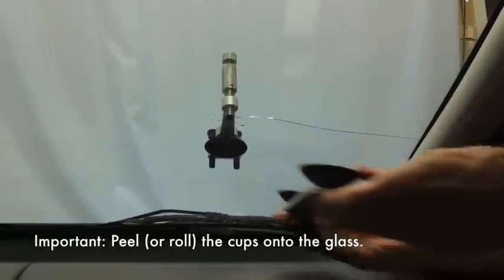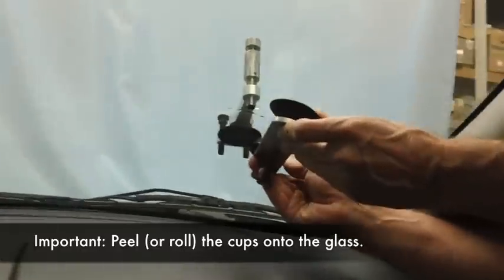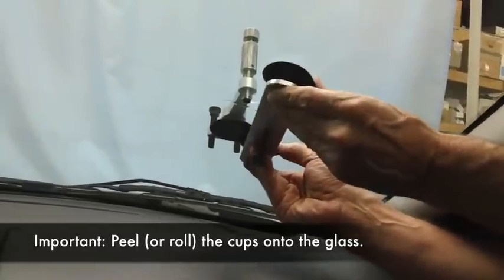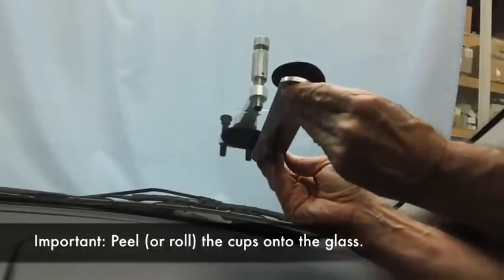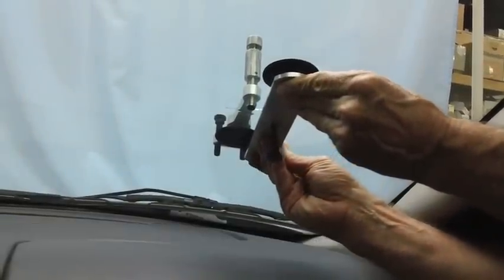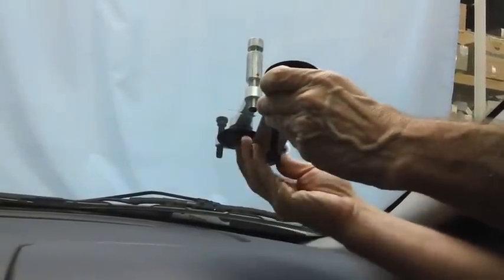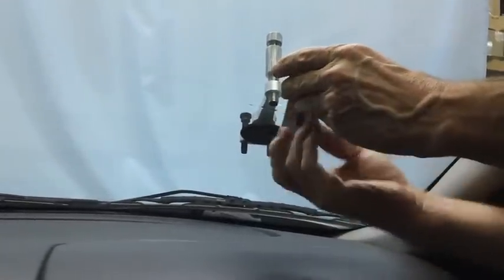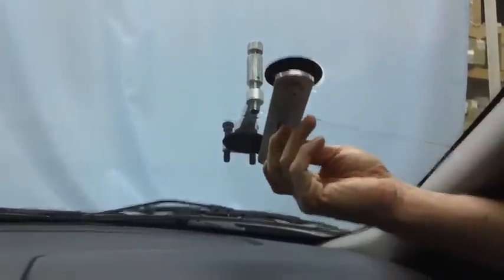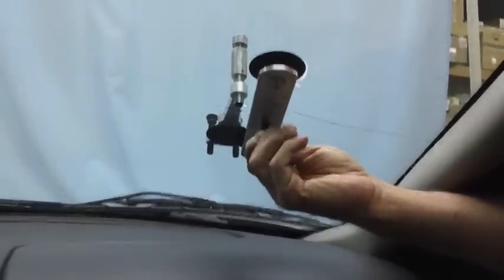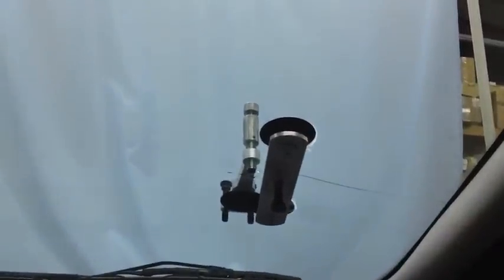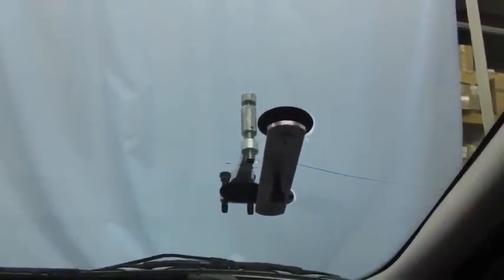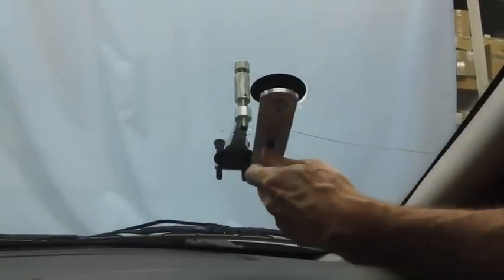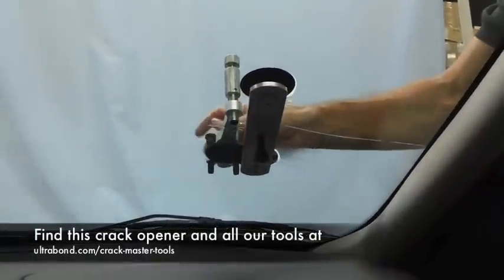When you place a crack opener on, you want to peel the cups back. You don't want to push them on, so that they're relatively flat. Just going to flex open the crack so we can get our crack resin in, while we're waiting for the resin to flow down the point.